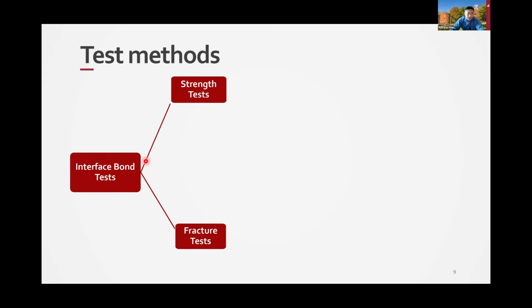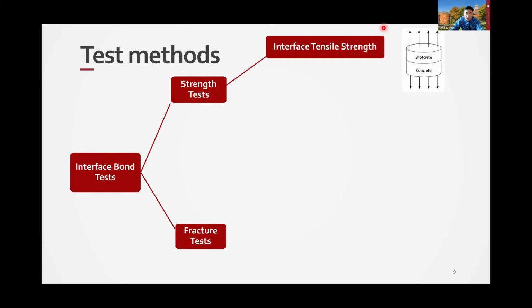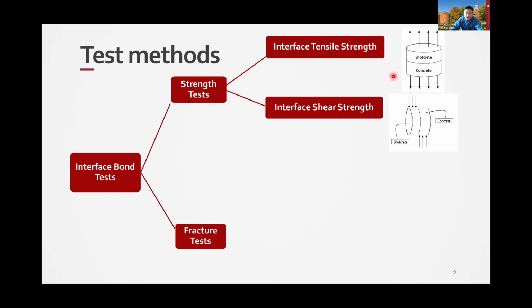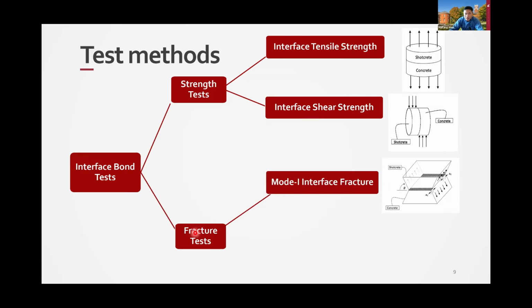In terms of the bond test, we have tried two types of bond strength tests. One is the strength test, the other one is the fracture test. For the strength test, one of them is the tensile strength. As you have seen from the slide here, you make a sample of the concrete and overlay, you pull it, and hopefully there will be a bond failure at the interface. The other one is the shear interface test. You support one side and push down from the other side, and there will possibly be a bond failure at the interface. And the other test will be the fracture test. That's the butterfly we're talking about.